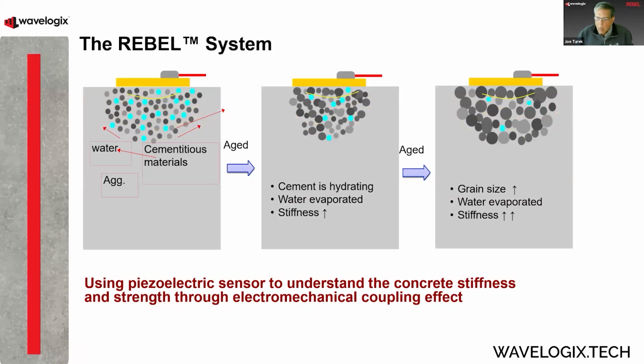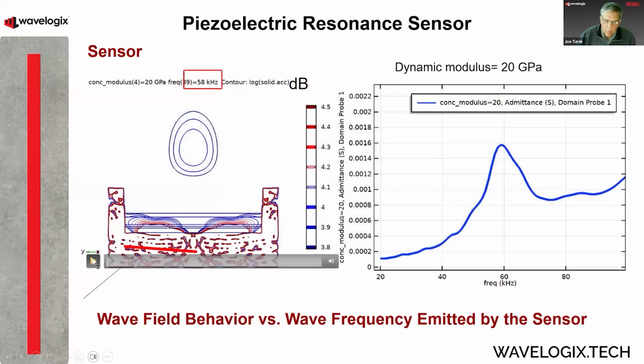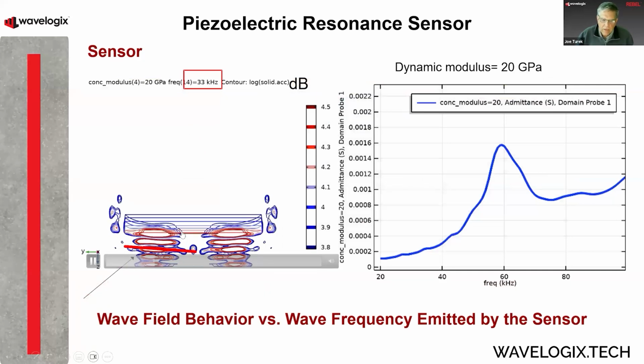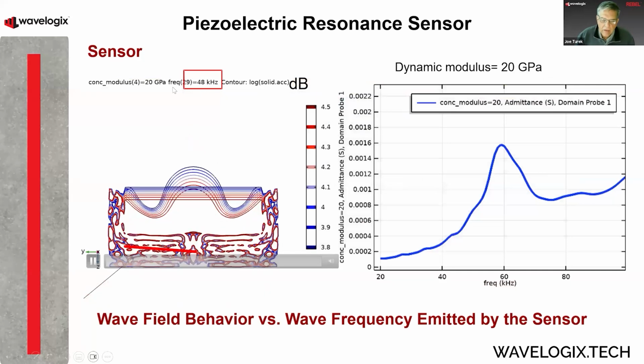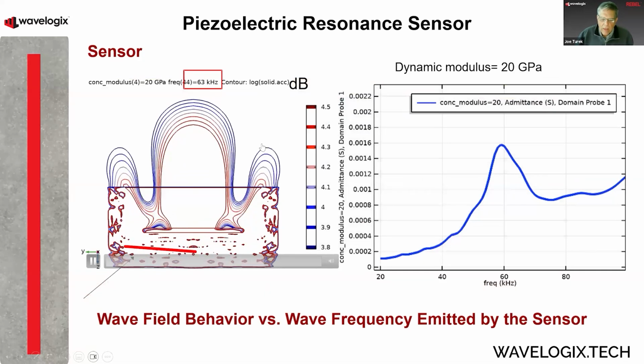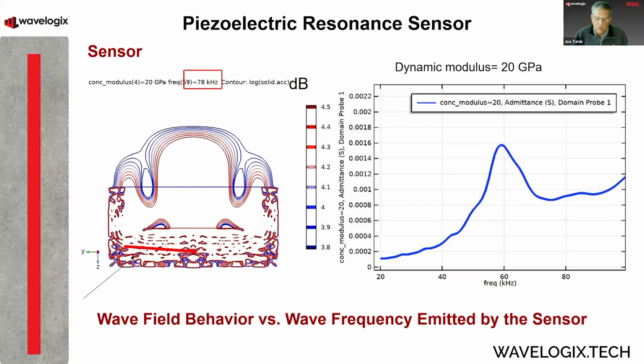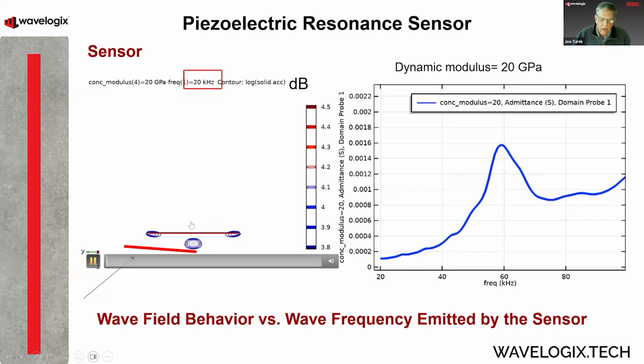How does our product work, and why is it different than cylinder breaks? Well, we're using piezoelectric sensors to actually create a wave that pushes itself into the concrete as it's curing. And that way we're measuring the impedance or the resistance or the pressure that wave is pushing against the cement. And the really interesting thing is that when you look at pressure, and here's a representation of what that wave pressure looks like as the frequency is changing, when you get to the resonant frequency of the structure, you will see the wave itself grow.